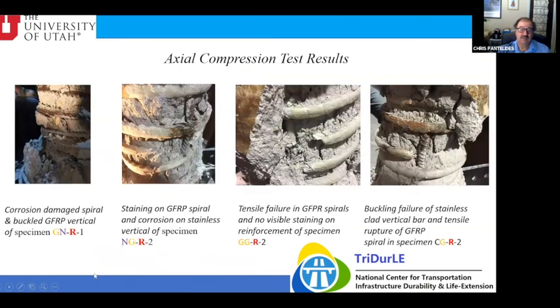So here are some results for all 4 different types of the specimens. So you see there is some damage, significant damage actually, for the stainless steel spiral, which may be surprising, but even stainless steel actually can corrode, as you can see here. Here you can see staining on the fiberglass spiral, even though the vertical is supposed to be stainless, but actually after 60 days, it did corrode some.